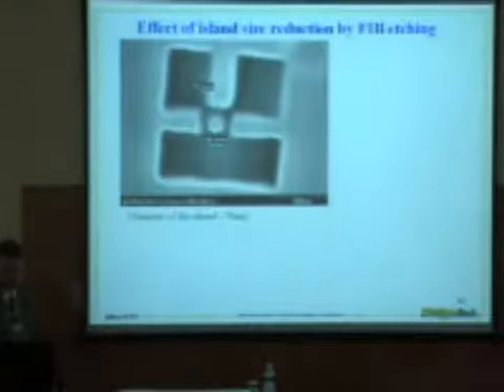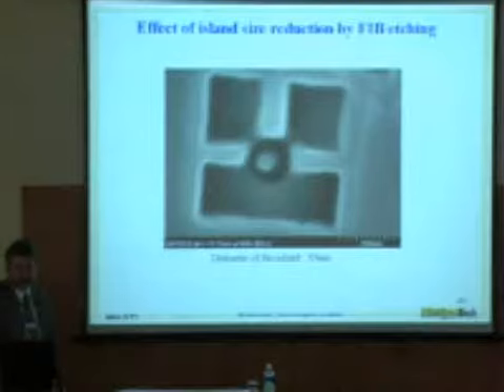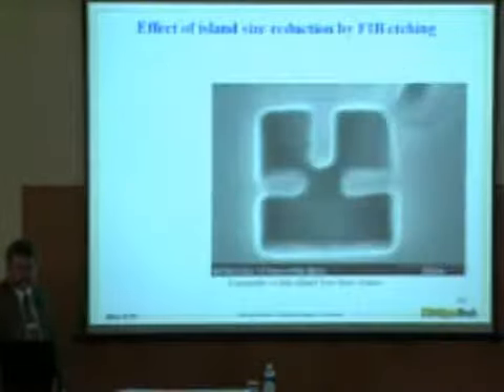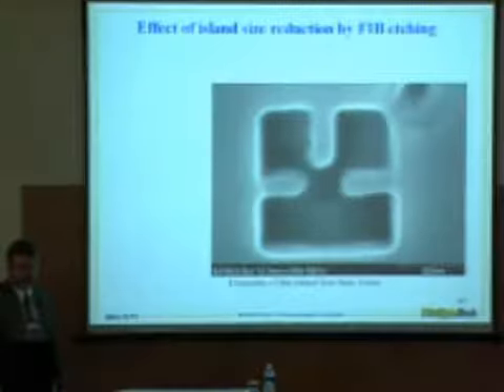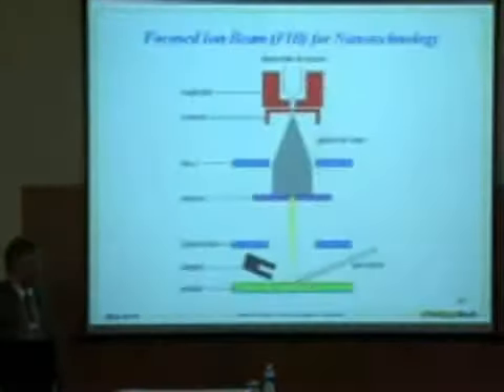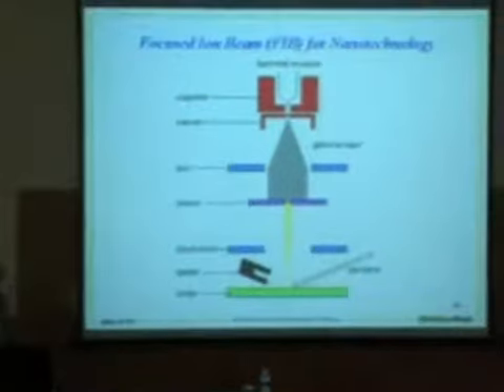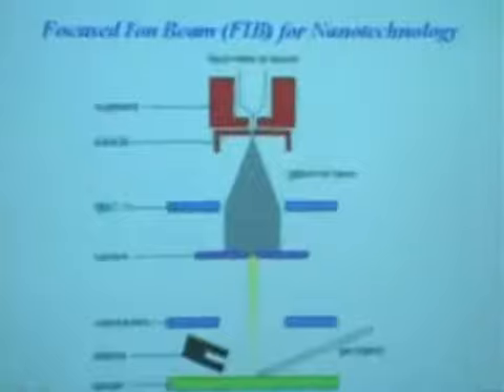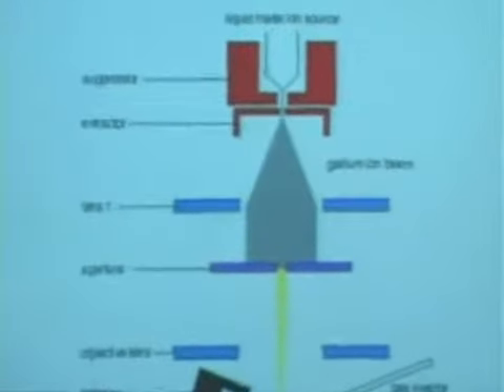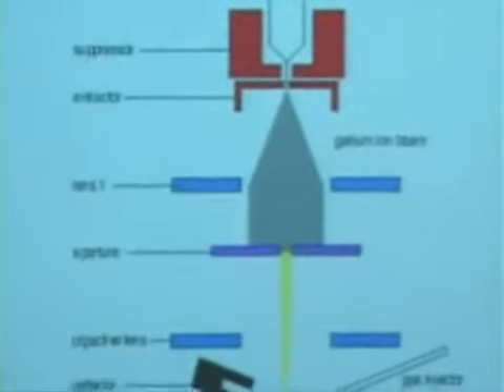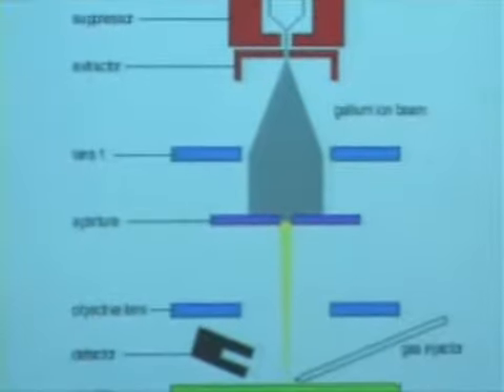So just some examples or some demonstrations of how this was done. We see at 50 and 45 nanometers that we can still produce quantum dots, but then at dimensions below 30 nanometers, especially in aluminum, which is a lower temperature material, we're seeing this causing a problem. So we thought, okay, we're not going to be able to get our 1 to 10 nanometer quantum dots by etching. We're going to have to come up with another technique.